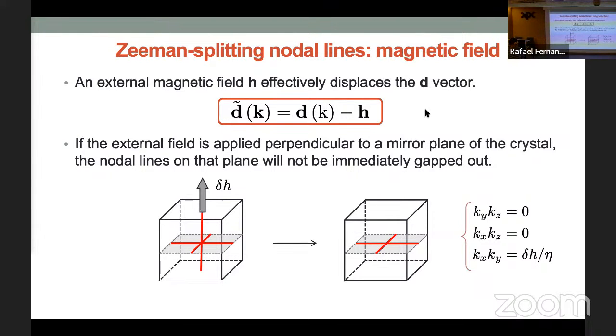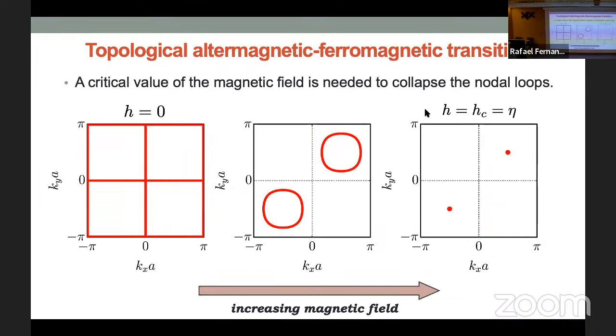What happens in this case? Well, the only way that you actually kill these lines is if I keep increasing the field. It's not a small field anymore. And here's a picture in the lattice, in the Brillouin zone. These are the nodal lines. They form these squares. The moment I apply a field, you see I only get two of them that remain, and they form these loops. And all I can do is have these loops collapse. And when they collapse into a point, that's finally when I lift all the gaps.